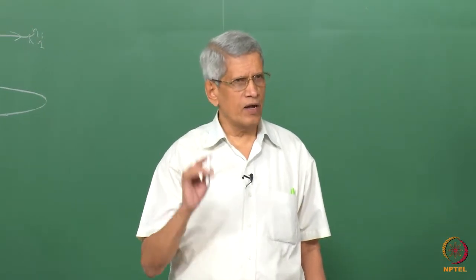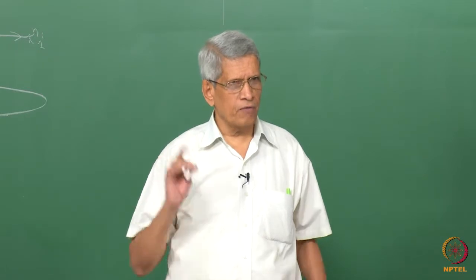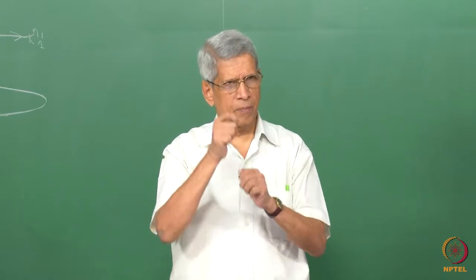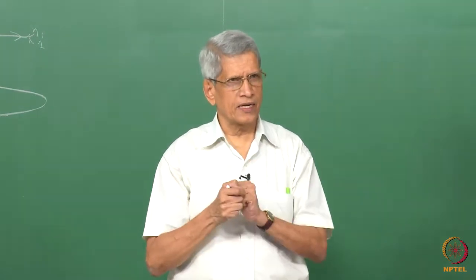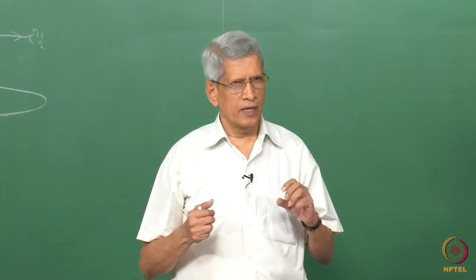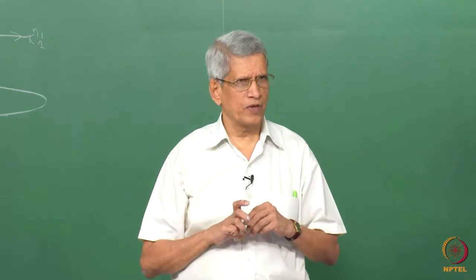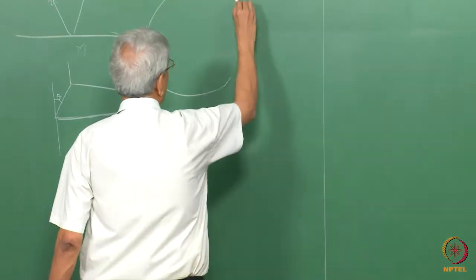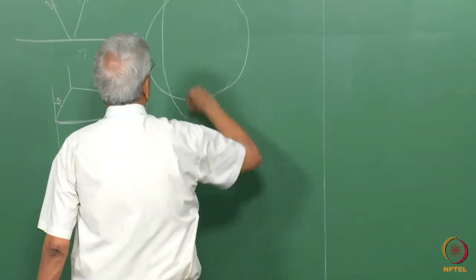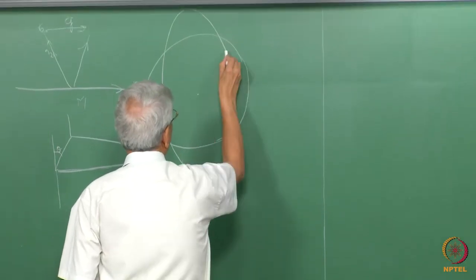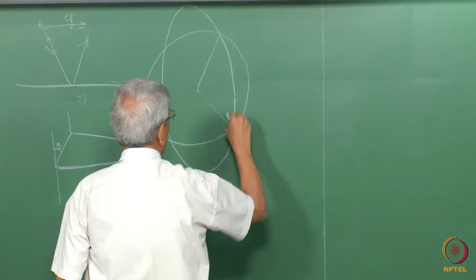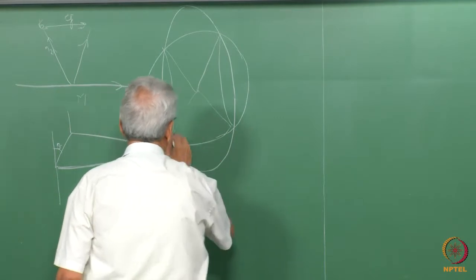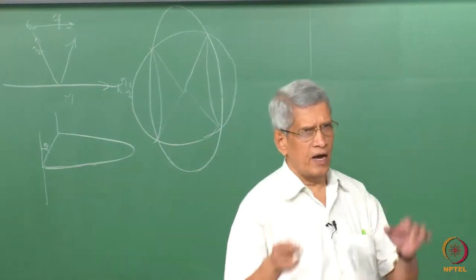And if strain is involved in all the 3 directions, then what happens if we take a sphere of the sample and apply homogeneous strain in all the 3 directions? It becomes like an ellipsoid. This ellipsoid intersects the sphere along 2 circles on the circumference.